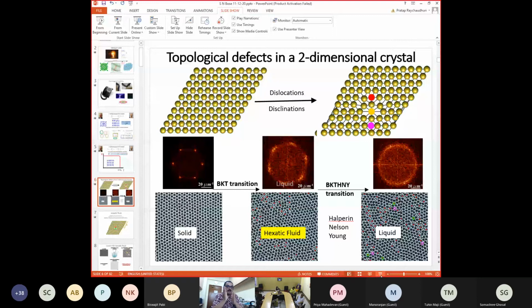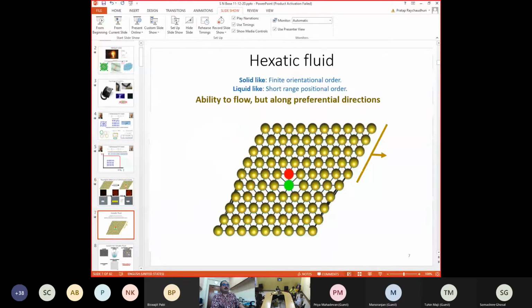More importantly, like a liquid, it has the ability to flow. So it's a fluid state. It's not a solid state. But it cannot flow uniformly in all directions. So a hexatic fluid has a preferential flow direction. It flows preferentially along the principal axis of the orientational order. For example, it can flow by plane sliding like this and the dislocation moving out, but it cannot flow easily in a direction that is, let's say, in between two principal axes, which is 30 degrees from a principal axis. Okay, so it has the ability to flow but along a preferential direction.